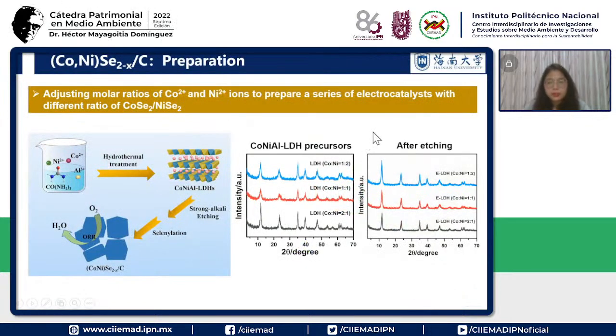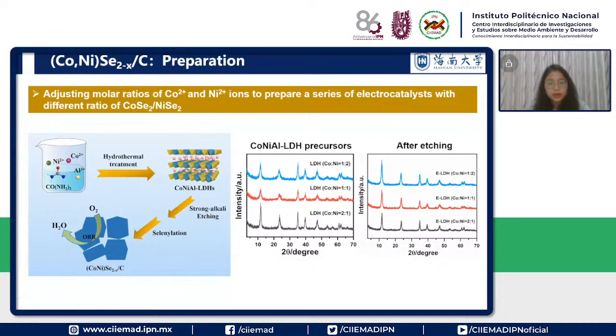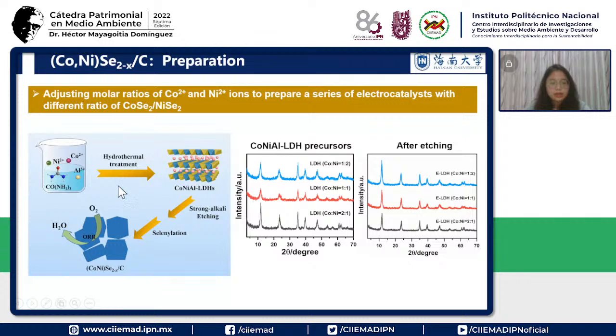So we are going to report 3 works based on these strategies. The first one is the cobalt nickel selenide supported on carbon. It shows at the left here the preparation. We adjust the molar ratio of the cobalt and the nickel ions to prepare a series of catalysts with different molar ratios of the cobalt selenide and the nickel selenide.